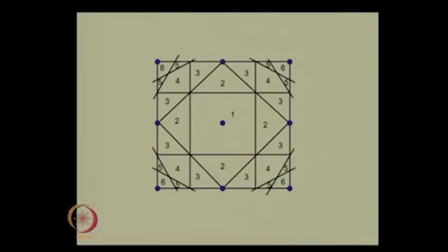In that reciprocal lattice we would identify the Bragg planes similar to what we have just done. Once we have identified the Bragg planes, using the definition of what is the nth Brillouin zone, we will identify the nth Brillouin zone. So, the nth Brillouin zone requires you to cross n minus 1 Bragg planes, but prevents you from crossing the nth Bragg plane. So, between the n minus 1th and the nth Bragg plane you have the nth Brillouin zone. Okay. So, this is something that we have seen in 2 dimensions.